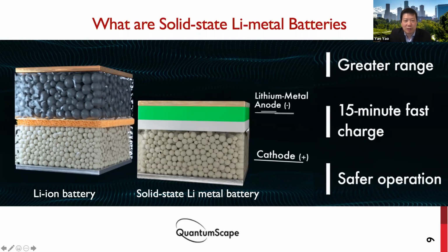In a solid-state lithium metal battery, you can use the same cathode, but replace the porous polymer separator with a ceramic separator. You could use lithium metal as the anode, or in the anode-free design, lithium metal could be plated during the initial charge process. Due to the reduced volume and mass compared to lithium-ion batteries, lithium metal batteries can potentially double the energy density from 250 to 500 watt-hour per kilogram. This could enable a greater driving range, 15-minute fast charge, and safer operation due to the non-flammable electrolytes involved.